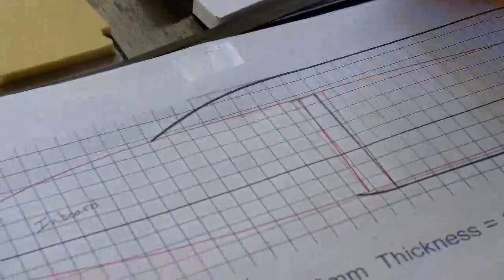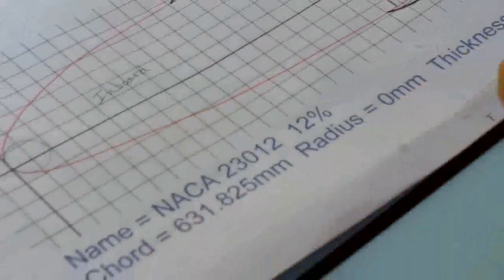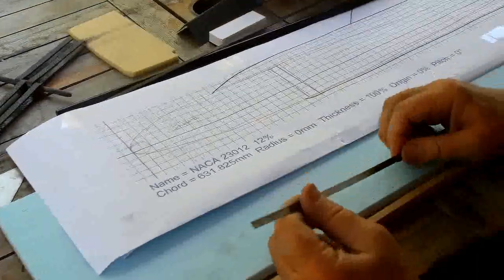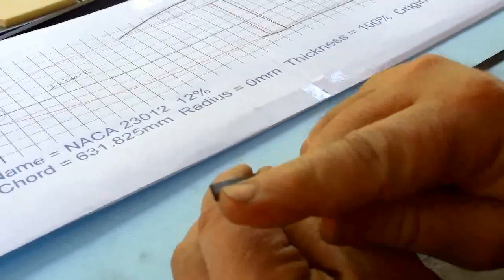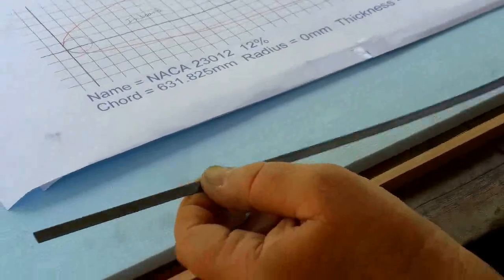Now, since I built my first wing, these new materials have come out. This is a strip of pultruded carbon fiber. And you can see it's very small. This is 0.015 of an inch thick. So about a 64th of an inch thick. And it's a quarter inch wide. This strip, much smaller and lighter than the wood stick. This pultruded carbon fiber strip will take 1,800 pounds of load. 1,250 for the stick, 1,800 for this. So the carbon fiber will take much more load for less weight.